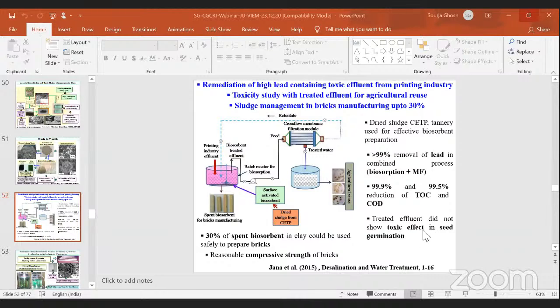So it did not show any toxic effect in seed germination, because about 99% lead removal had been achieved with 99.9% removal of TOC and COD. So this had enabled detoxification of the hazardous effluent. So the treated effluent can be safely reused in either agricultural or any other applications. And the product is that 30% of spent biosorbent in clay could be used safely to prepare bricks. So this is the outcome of the project. Apart from detoxification of a toxic effluent, it can be producing biosorbent-incorporated bricks. So these bricks showed reasonable compressive strength. So this is the achievement in our work.